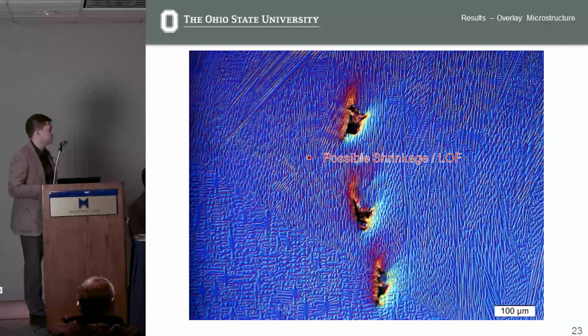Also, some similar defects, some possible lack of fusion and shrinkage defects were detected in the weld metal itself. But again, these are pretty small defects with respect to some defects that are possible in the standard processes.